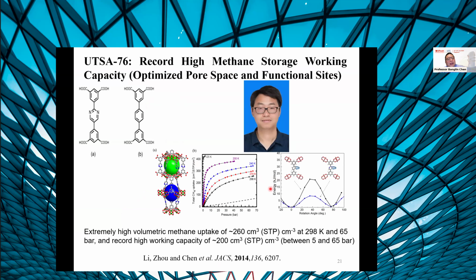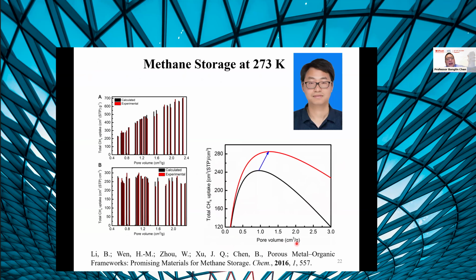And during our studies, we kind of unexpectedly found that changing from benzene to this pyrimidine, with nitrogen, will have a little bit stronger interaction with methane. So the methane storage is quite significantly improved. And this is because of the stronger interaction and rotation, a low energy barrier for the rotation. So that time, this was a record methane storage capacity. Again, we realize the methane storage empirical formula under different conditions.